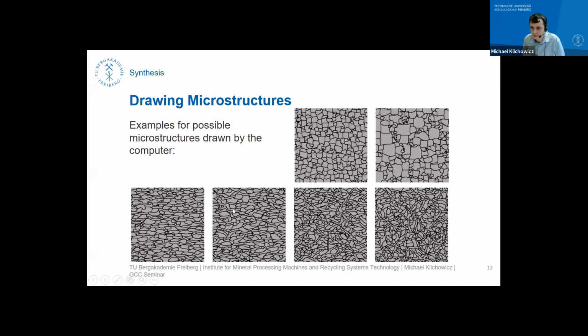And what can we do with this procedure? Here are some example microstructures. They are all drawn with the program, and we have a microstructure here with more or less equal sized grains. And in the next microstructure, I just changed the variety of the grain size. And you see, in comparison, you have much larger grains here. And for example, at the bottom side, I used elongated grains for this example, and on the left side, they are all orientated in one direction, and with each next image, I increased the variety of the orientation, resulting in a more or less unorientated microstructure on the right side.